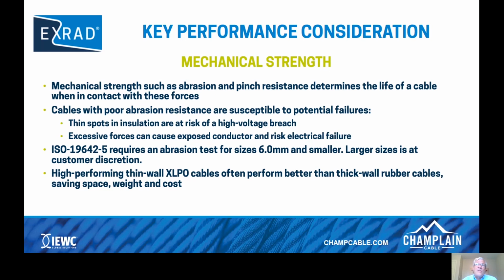The best case I can think of in this situation is when a vehicle is serviced and tools are getting close to some of the cables and might cause pinching and other things like that. ISO 19642-5 requires abrasion tests for 6 millimeters squared and smaller. Larger sizes are at the customer's discretion. Now, I should mention that most of the available conventional test equipment for abrasion, sandpaper abrasion and scrape abrasion, is a little bit cumbersome when it comes to testing larger sizes like 35 and 50 millimeters squared.